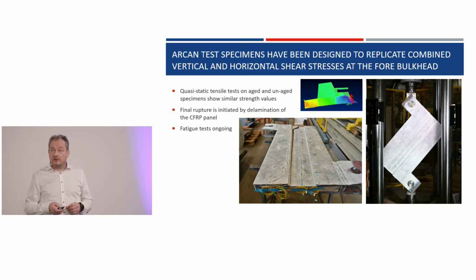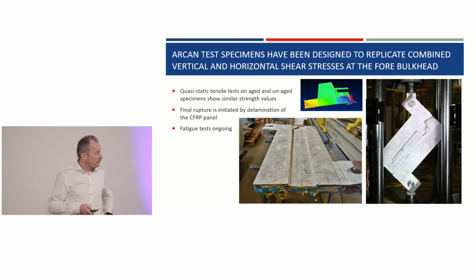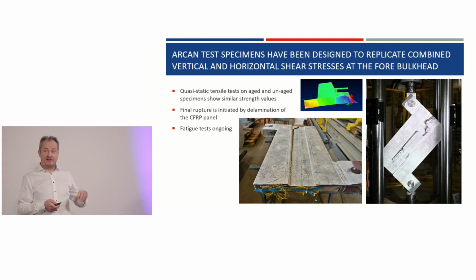The Arcan tests, you see at the right how the specimen fails in a static test. So we did quite a lot of these tests again, but all tests, aged and unaged, in the static load reached again the same level of strength, and again damage always started, maybe you have seen it on the short movie at the right, at the top right there in the composite, again delamination, and then transferred through the composite, and afterwards led to some failure at the interface.